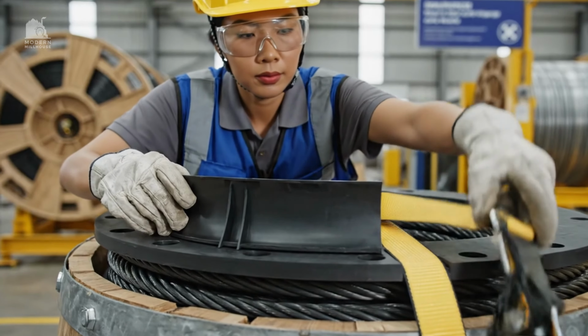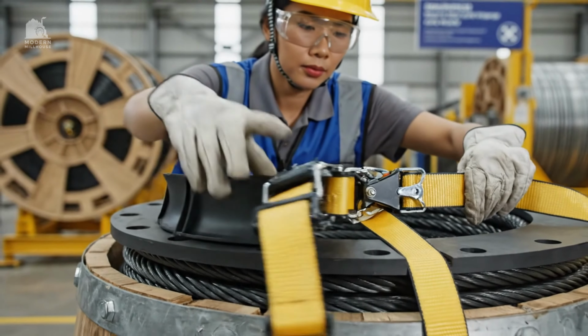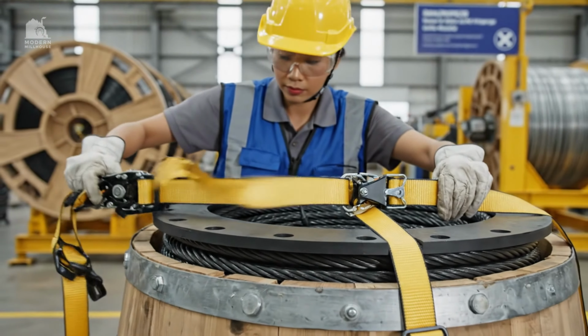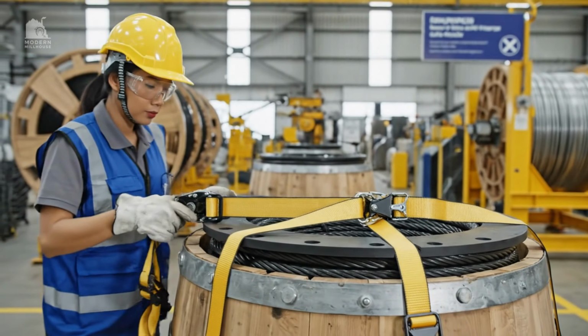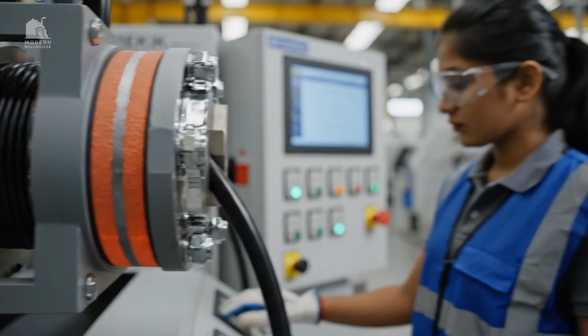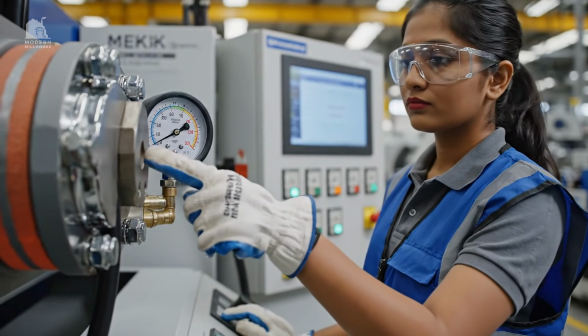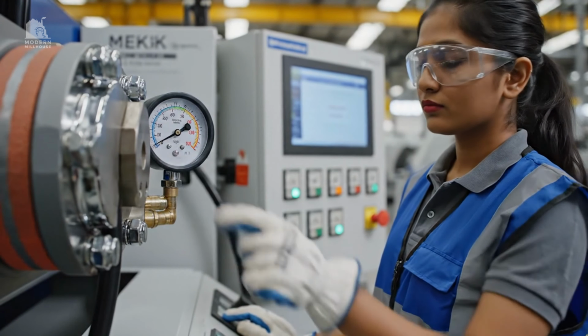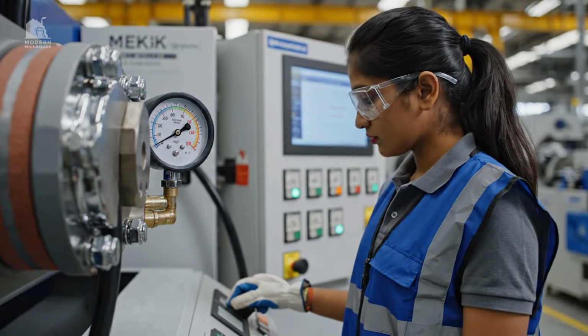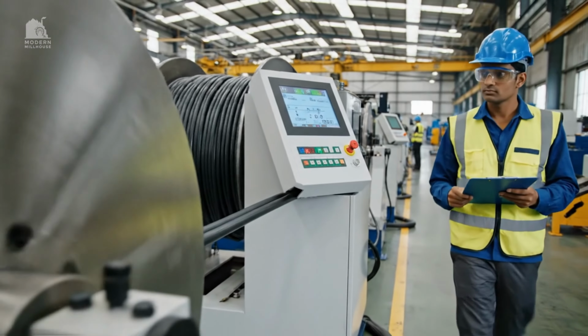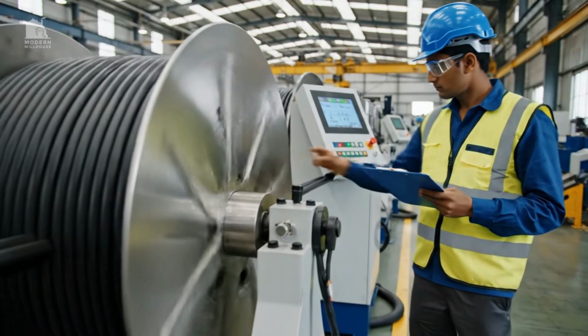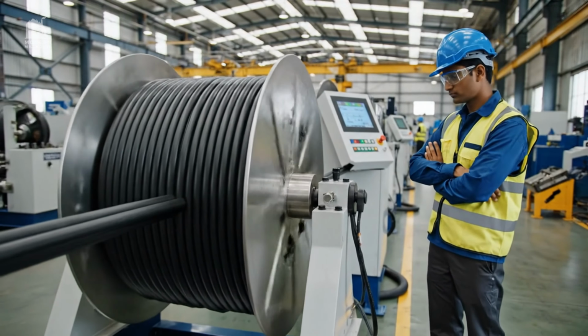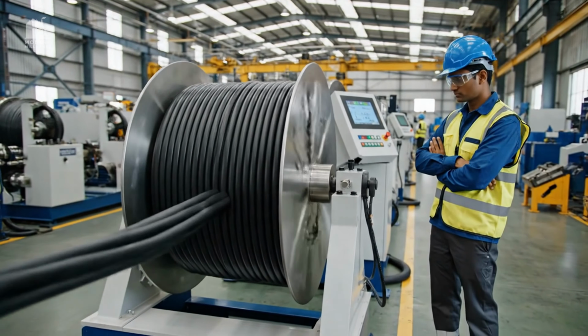Drums are protected so the outer jacket doesn't rub against flanges during vibration in shipping. Jacket quality depends on stable melt pressure. Too low creates voids, too high risks scorch. Final diameter gauges confirm the overall size, keeping the cable compatible with connectors and conduit.